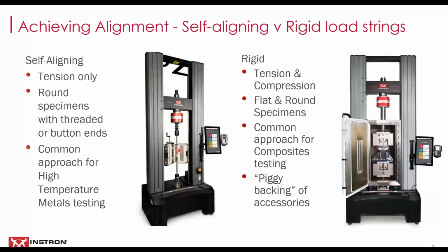This is very suitable for round specimens, but they need to have threaded or button ends because those specimens need to be coaxial with the center of rotation of the flexible couplings in order for this to self-align correctly. It is a common approach for high temperature metals testing. There you see a high temperature furnace on this system, long rods into the furnace and these flexible couplings, and this is great for tension, completely inappropriate for compression.